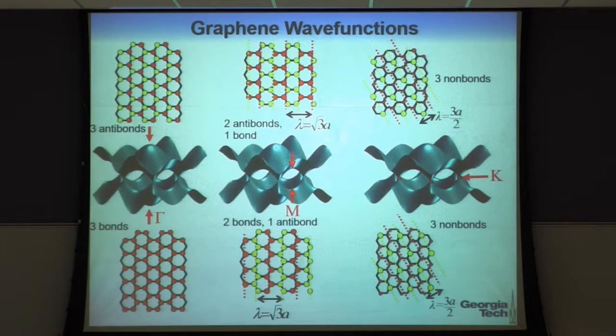But if you go to the K point, then what you'll find is that multiplying this by the correct phase factor, I get a wave function that looks something like this, which is I get a maximum here, I get some sort of minor maxima over there. These are all on the A sites, let's say. Whereas over here I get exactly the same wave function, but those maxima occur on the B sites. Well, those are identical in energy. It's just shifting the wave function from A site to B site, but there was nothing to really distinguish them. And so these two things are degenerate in energy, and that's why at the K point we have this degeneracy between the bands that came from the anti-bonding states and the bands that came from the bonding states.